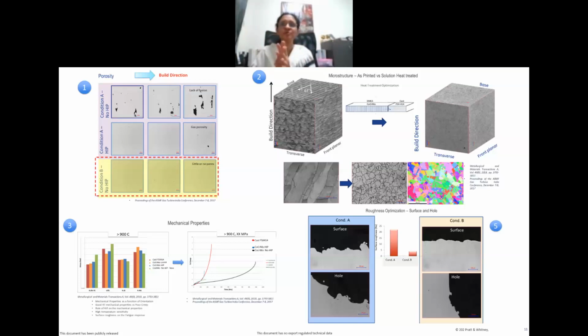You just need to do the reproducibility, because additive is fraught with build-to-build variability. So you need to establish that in challenge number 3, in terms of orientation dependent mechanical properties, and then you make the best use out of it. And that's what we did in this application. And then next comes another, actually this is 3 and 4. I have combined multiple things in this slide, and then go into what is a big challenge in additive manufacturing. You might have all heard about it, it is definitely surface roughness. Because in a conventional casting or a forging, we do have an allowance that we give for machining.